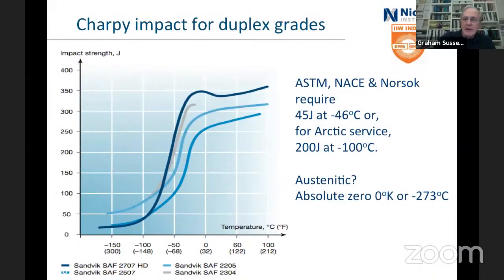And Charpy impact. This is data for 2707, 2507, 2205 and 2304. So going from hyper to super to ordinary or standard to low. And yes, you can see that down at -40, well, it starts dropping off at about -20 or so, but you can get well down.